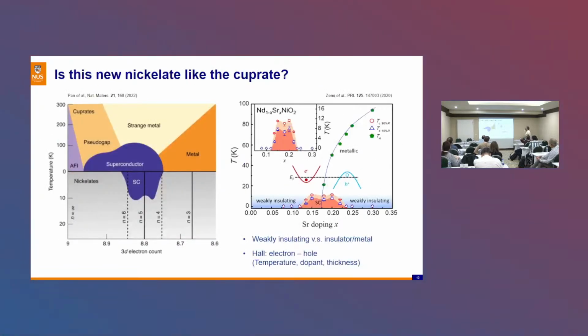Right, so is this new nickelate really like cuprate? Here, if we look at the 3d electron counts, when we plot the Tc as a function of 3d electron count, it kind of replicates what we have in the cuprate, right? Even though within a smaller doping range, it is within the same range of 3d electron counts that produces superconductivity. This is also where the Ruddlesden-Popper compound picture comes in. If you start with a 3-layer system, you are still away from the dome, so you probably need to play with the dopants. While in the case of Julia's, she did the 5 layers, and then you come directly, simply based on self-doping, within the regime of the superconducting nickelate dome.